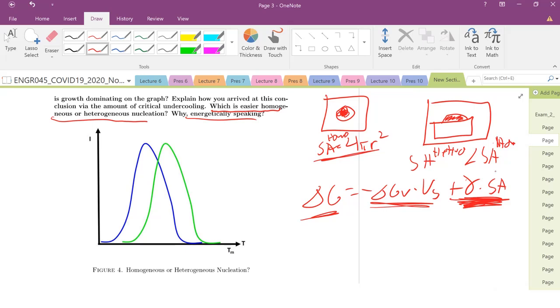As compared to homogeneous nucleation. So looking on this curve now, using the same idea, we need to figure out which curve is homogeneous nucleation. Looking at this steady state nucleation rate, remember, it is composed of 2 terms. One is our delta G from nucleation. This component dominates at low temperatures, so we want to nucleate at low temperatures. At high temperatures, we have very low driving force for nucleation, again given in that delta GV term.